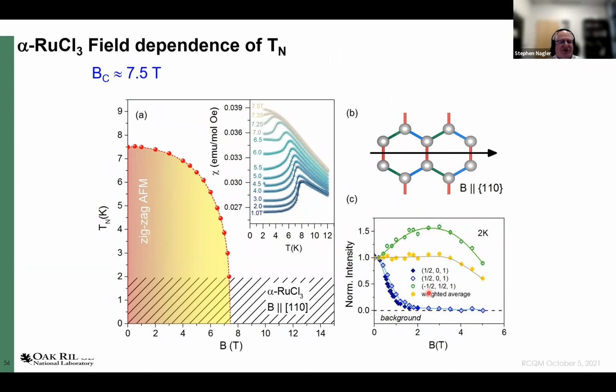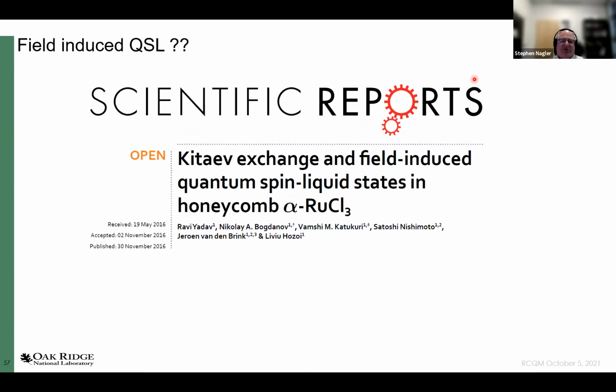Now, if one applies a field in the plane to this, a fairly modest field will actually kill this magnetic order. It turns out that the most sensitive direction to put a field is perpendicular to a bond connecting one ruthenium to the other. If you do that, at something like 7.3 or 7.5 Tesla, the magnetic order will go away. After this was discovered, and Jeff Lynn was involved in some nice work looking at this as well at NIST, it was hypothesized that this actually resulted in a field-induced quantum spin liquid state. So it's interesting to look at this potentially in a field.